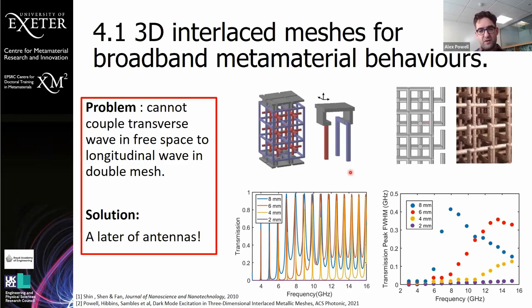And we can see that if we model the transmission through this, this is modeling for a 10-layer structure for perfect conducting materials, there's no loss, there's no surface roughness, we can see that the full width at half maximum of each of these Fabry-Perot peaks corresponds to the envelope of the antenna resonance. So what this tells us is that actually